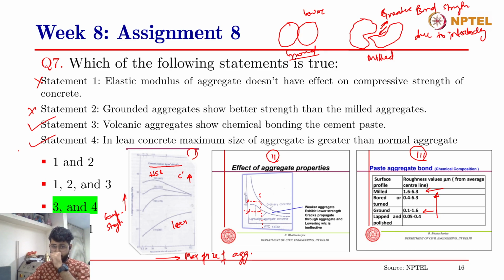In lean concrete, the maximum size of aggregate is greater than normal aggregate, meaning that the allowed maximum size of aggregate could be higher due to an allied increase in the compressive strength as compared to normal concretes. So the correct answers are 3 and 4.